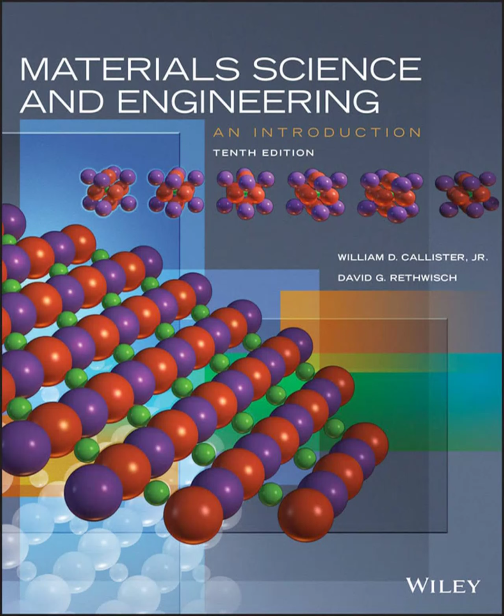And we saw that prevention is multifaceted, involving careful material selection, altering the environment using inhibitors, smart design, applying coatings, and employing powerful techniques like cathodic protection. Then we shifted gears, noting that oxidation in gases is also crucial, governed by the properties of the oxide scale, summarized by the Pilling-Bedworth ratio. And finally, we contrasted this with ceramics, which are generally very inert, and polymers, which degrade through physiochemical routes like swelling, dissolution, and bond rupture caused by radiation, chemicals, or heat.